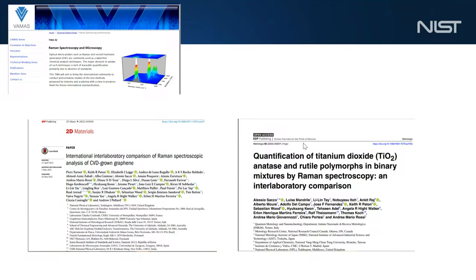In the other example, we have titania. And in this case, we found that Raman is very good at differentiating anatase and rutile. These are two different forms of titania often found. Again, titania is produced in mass numbers. It's not always nanoscale, it can be microscale. But Raman really proved to be a very sensitive technique, if the protocol was followed well, to differentiate the two polymorphs. So I'm just giving you two examples. Again, we have many of these under study.